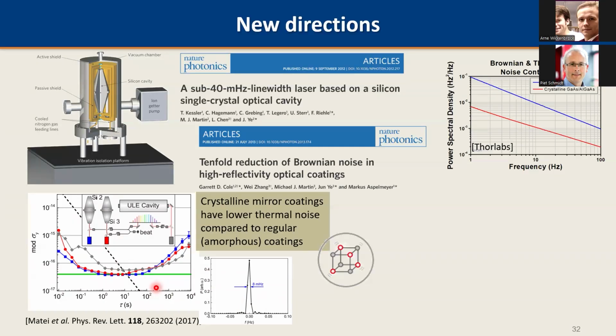Aluminum, indium, gallium, no, aluminum gallium arsenide or InGaAs coatings. I don't remember the composition, but it was grown by atomic layer deposition, single crystals essentially, and they could demonstrate a tenfold reduction of Brownian noise in these highly reflective optical coatings.